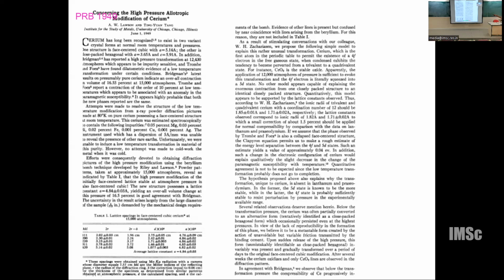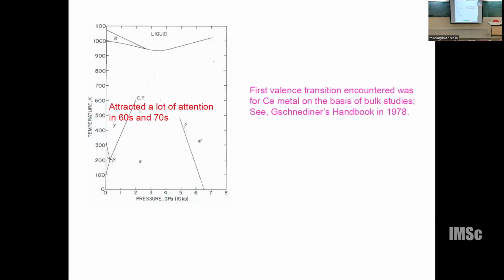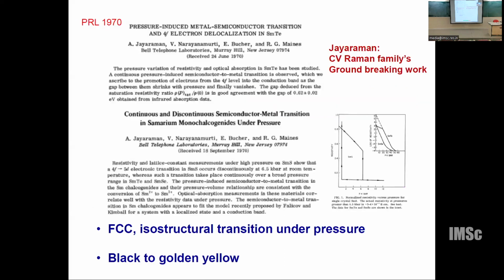And then at high temperature, it behaves like magnetic. At low temperature, it was not behaving magnetic. The susceptibility was low at low temperature. So these were confusing for some time. And then, this is a very interesting phase diagram. I should not spend my time on it. This cerium metal has a very interesting phase diagram as a function of temperature and pressure. Let me not spend my time.